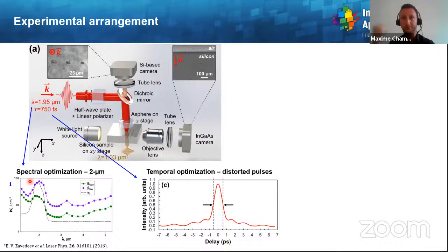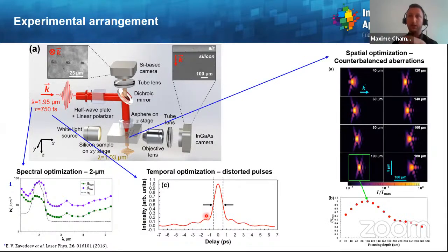Second, we have used sub-picosecond pulses, so femtosecond pulses, but that time with distorted pulses. As you can see here, the autocorrelation trace, one can see that there are a few bumps inside the temporal profile, which can be explained by some satellite pulses near the main peak. And third, we have used a spatial optimization, which consists of counterbalancing the aberrations provoked by the aspherical lens shown here, so counterbalancing those aberrations with the aberrations inevitably provoked by the air to silicon interface.